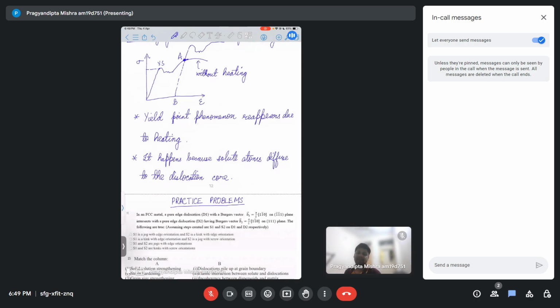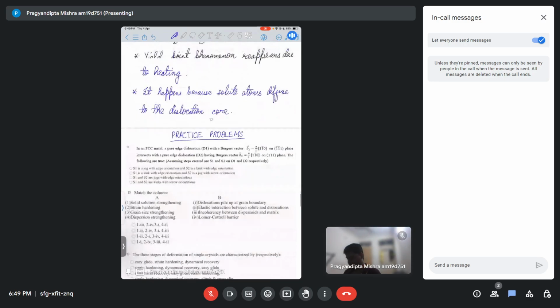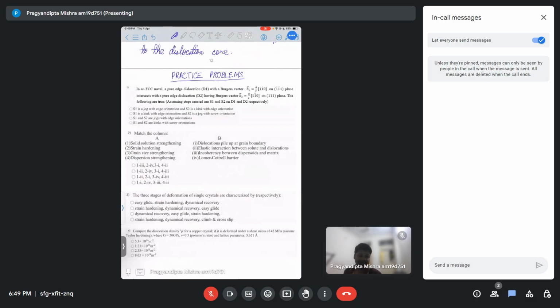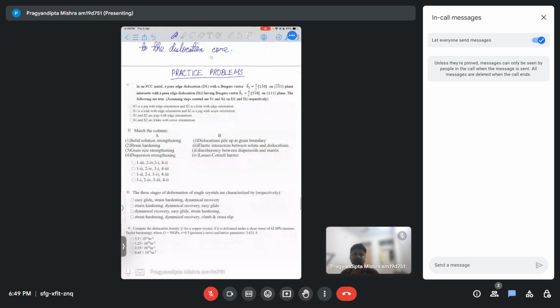Okay, so with this we come to the end of the theory part. Now let's move on to the problems. Okay, the first question: in an FCC metal, a pure edge dislocation D1 with a Burgers vector B1 equal to a/2 [1 bar 1 0] on the (1 bar 1 1) plane intersects with a pure edge dislocation D2 having Burgers vector B2 a/2 [1 bar 1 0] on another plane. The following are true, assuming steps created are S1 and S2 on D1 and D2 respectively. Okay. So what we are seeing is a pure edge dislocation interacting with another edge dislocation having Burgers vectors which are parallel, right? Or is it perpendicular? Are they parallel or perpendicular? Burgers vectors are parallel, right?